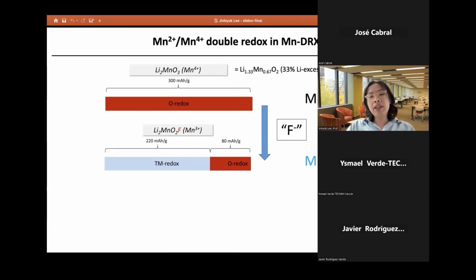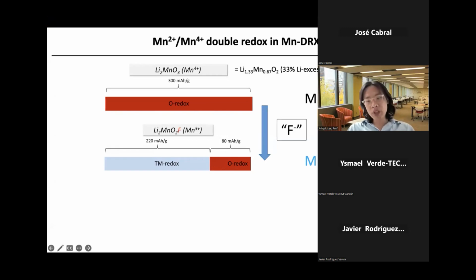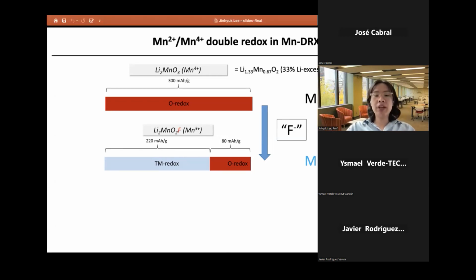So to get this, in this manganese oxyfluoride, the manganese oxidation state starts from manganese 3+. Because of this, if we extract lithium from the structure, we can at least get one electron coming from the manganese 3+ to manganese 4+ oxidation, right? So we certainly get some capacity from the transition metal oxidation.